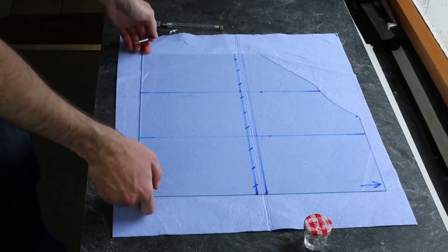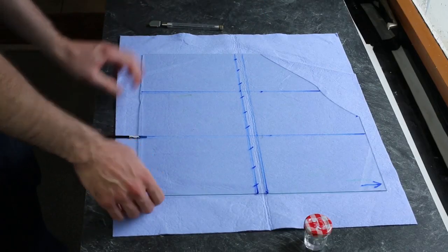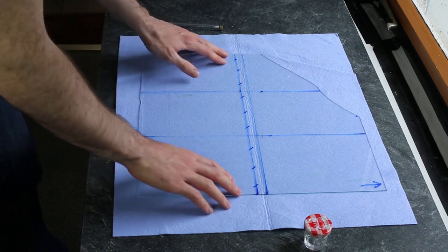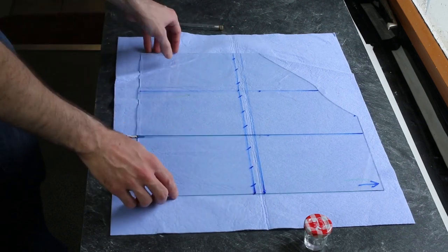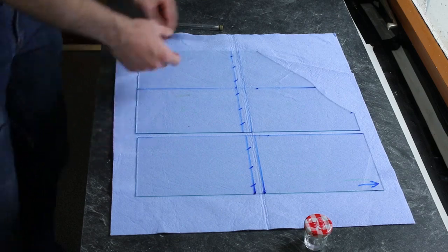Always make the shorter cut first. To get the best cut possible, you always want to cut the glass plate in halves. If your first cut failed because you released pressure halfway through the cut, you can always turn the glass plate around and try again. I place the brush handle under the cut and lightly press down on both sides with my hands. This should yield a clean break of the glass.